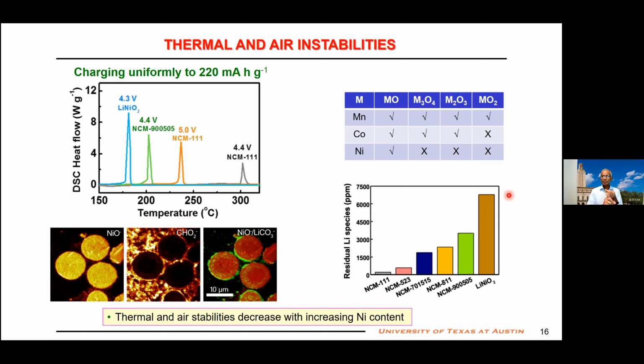when we increase the nickel content, meaning going from 50% nickel to 60% nickel is not the same as going from 80% to 85% nickel or 90% nickel or 100% nickel. So that's what we are dealing with. Right now, 60% nickel is commercial, 80% nickel has some users, but some still have difficulties. But the trend is, can I use 90% nickel, 95% nickel, or even 100% nickel? That is the trend. And one of these days it will happen.